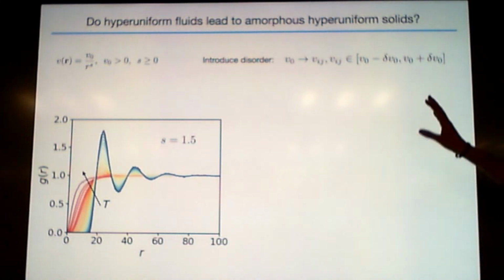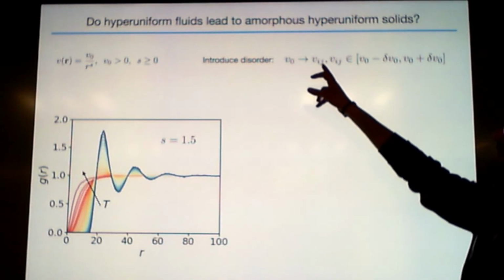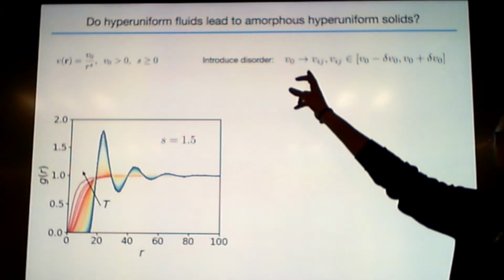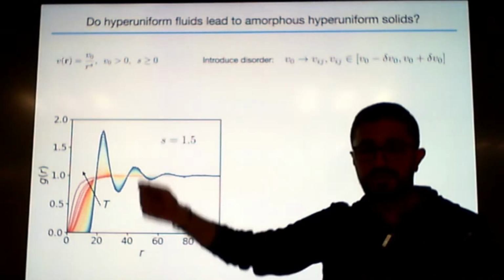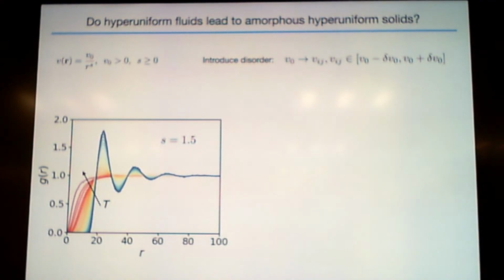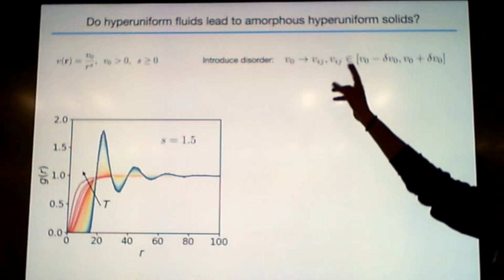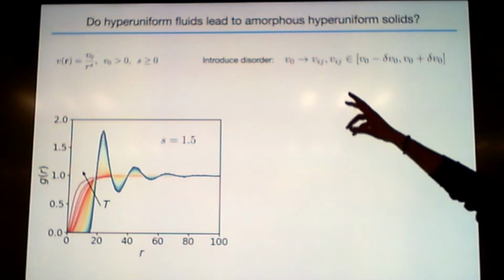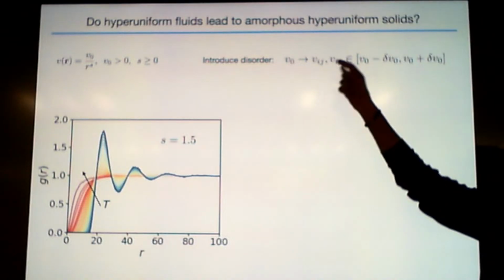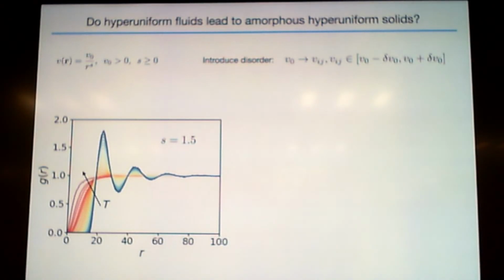You may wonder why we chose this weird Vij. There are some technicalities. Instead of taking energy per particle pair, I could also take Vi per particle. But then, since I'm doing swapping, it happens that particles that are close, the energies Vi's and J's, are close to each other. They would like to stay closer, so you get a polycrystalline system. So in order to not run into this technical problem, I'm using these Vij. So if there are n particles, there are n times (n minus 1)/2 values of Vij, pairwise.